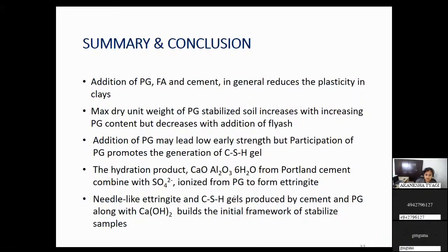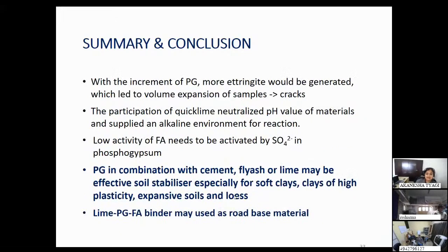And when Portland cement reacts with the phosphogypsum, ettringite is formed due to the presence of sulfates. This ettringite and CSH gels, produced by the cement and the phosphogypsum, build an initial framework to stabilize the samples. But if it is in excess, it may also lead to volume expansion and cracks. So this should be kept in mind when this particular material is being used for road construction.